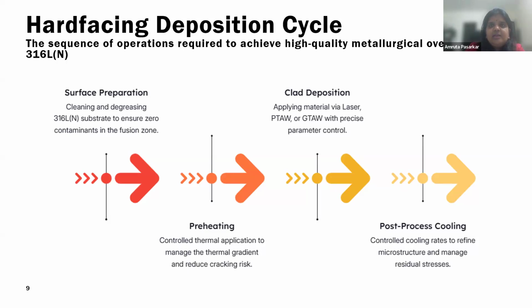After the preheating, the clad deposition is done by various methods. Any method can be used as per the requirement and as per the application of the industry. So the material is applied with either laser cladding, plasma transferred arc welding, or gas tungsten arc welding, and the parameters of these processes need to be decided so that the proper hard facing can be done on the base metal.